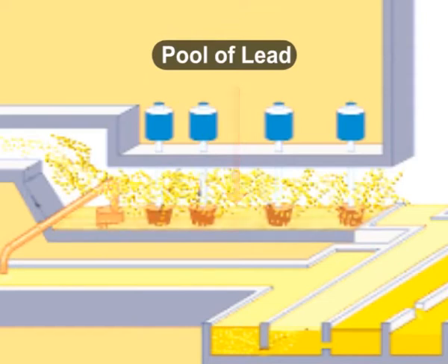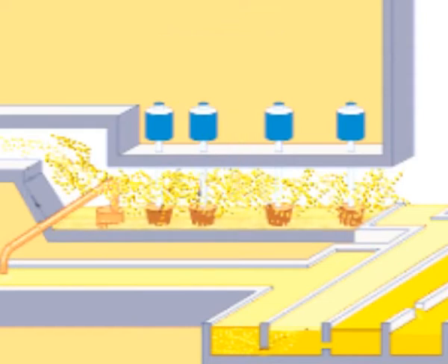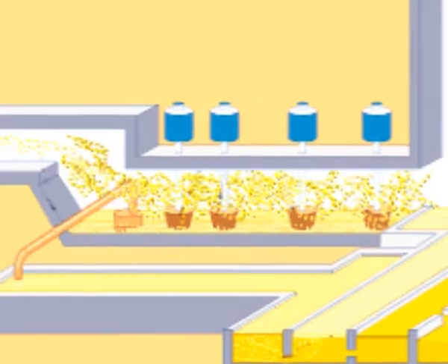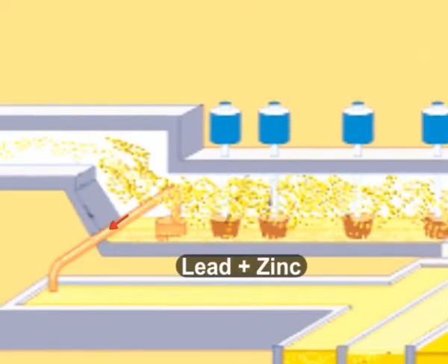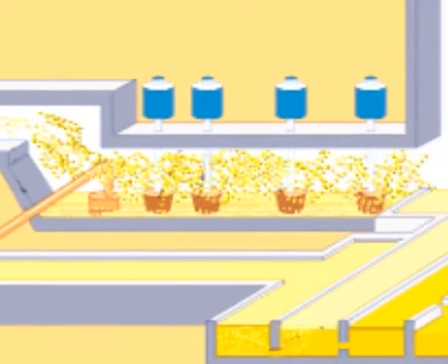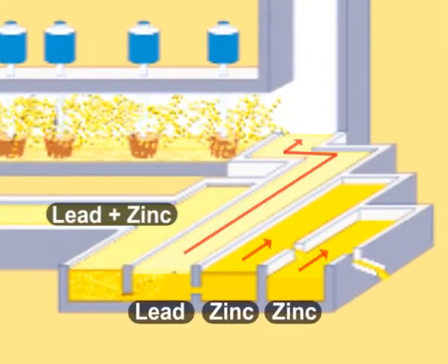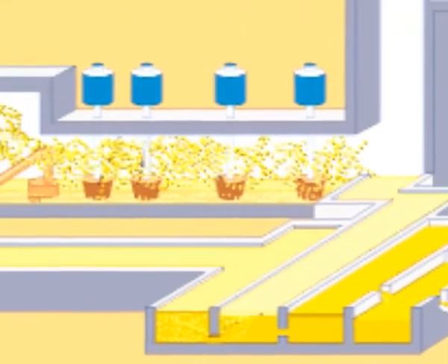The zinc vapor is absorbed into the lead, and by withdrawing the lead continuously and cooling it, the saturation point of zinc in lead is reached and molten zinc separates as a distinct layer on the surface. On removal of the zinc overflow, the partially cooled lead is returned to carry out further shock chilling.